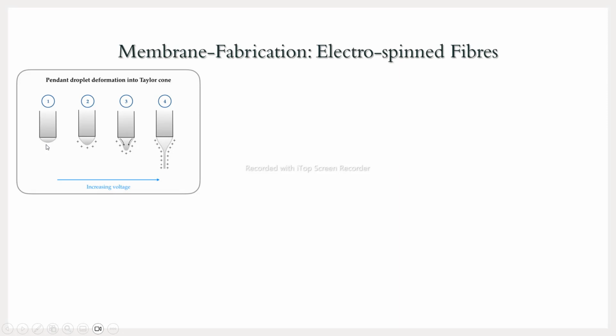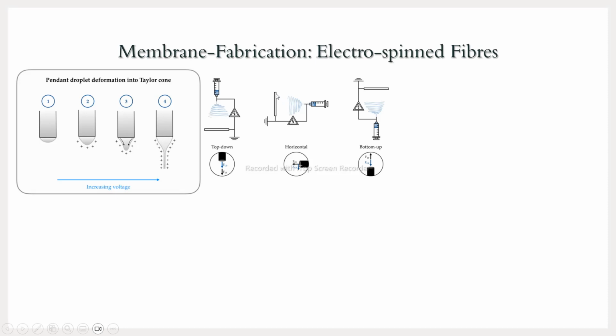The polymer comes on the tip of the syringe, which is the droplet of the polymer, and then the voltage is applied, and the droplet takes a conical shape, which is called the Taylor cone. As we increase the voltage, there comes a certain point where the fibers start emerging from the tip of the Taylor cone, and they get deposited on a metal plate.